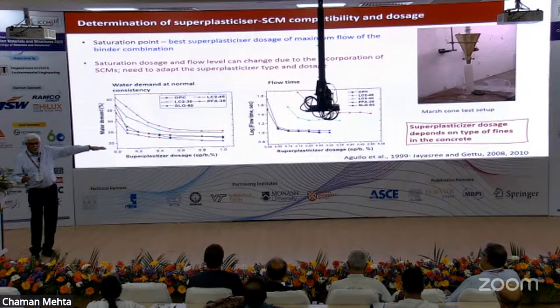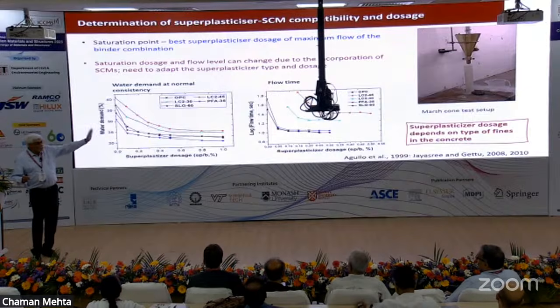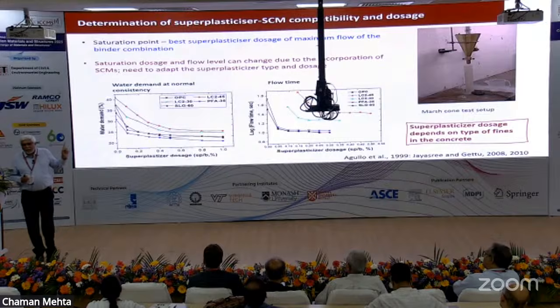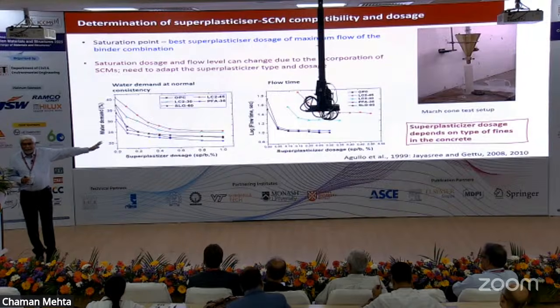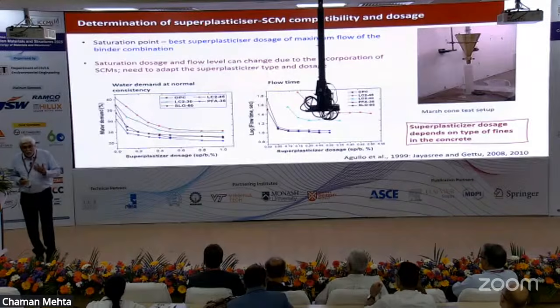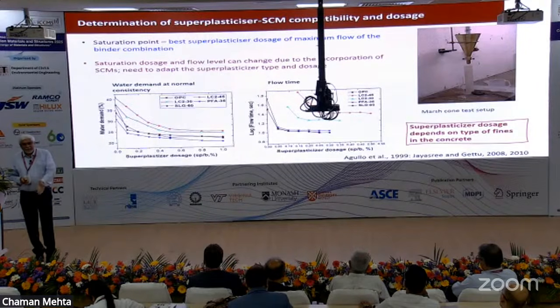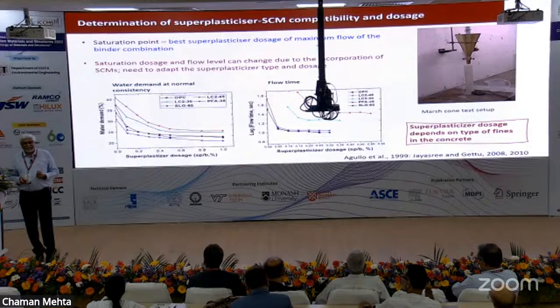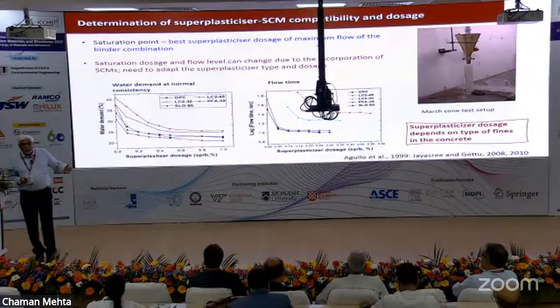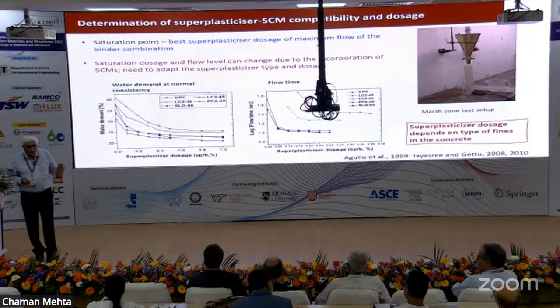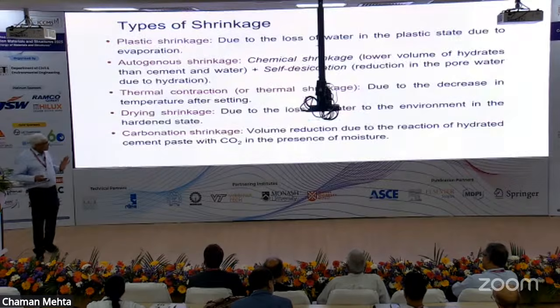Ordinary Portland cement is below. That means it flows faster. It needs less time. LC3 needs more, and LC2, which is without the cement, the limestone calcined clay, needs more time. So this already tells me that I'm going to have problems of workability. This means I have to put more superplasticizer or a different type of superplasticizer. Just at the paste level, within 1 hour, I can get this result. So if we can do this more often and have tools that the user can use at the site, then it makes things easier. So with this, now we know that if you're changing the type of cement, I have to change the superplasticizer, change the dosage. Don't try to do it with the same composition. It will not work. So these are things that we can look at.